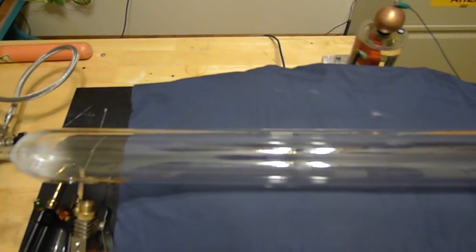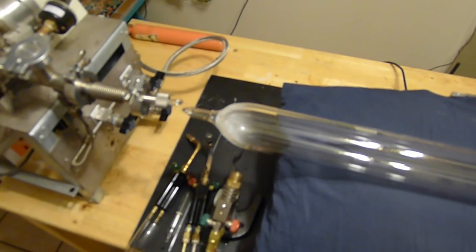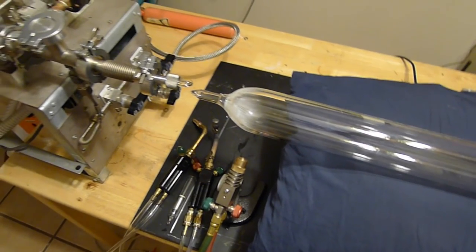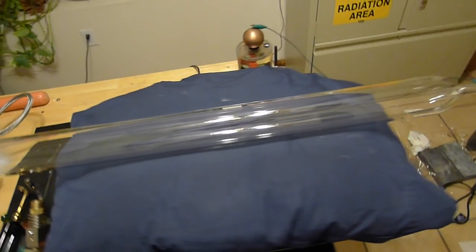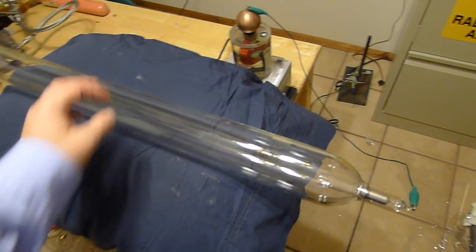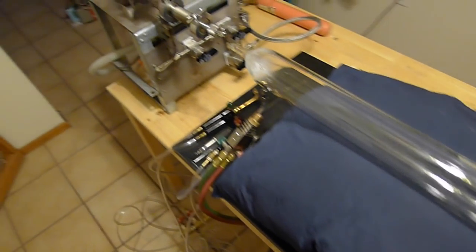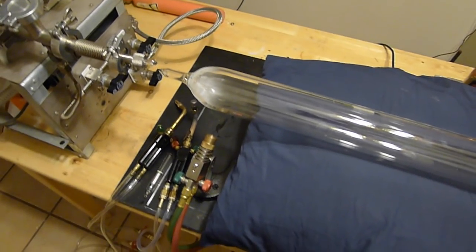The glass here is borosilicate. I really don't think anybody should try to do this with anything else. Borosilicate glass is easy to work with and does not require extensive annealing or difficult annealing practices. I would recommend that's where you start even though it is more expensive than soda glass.